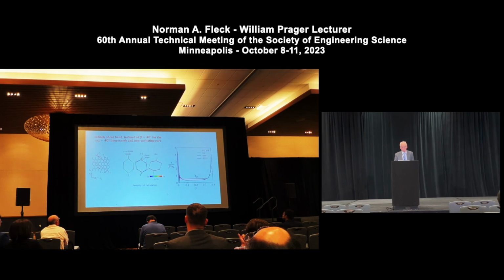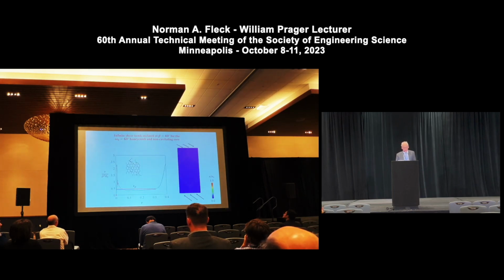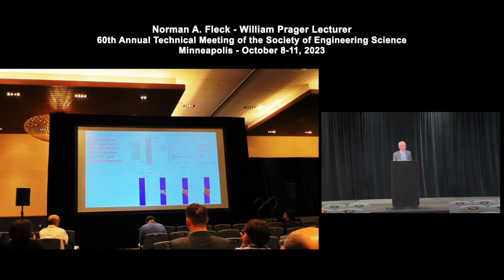So here's the simulation, finite element simulation of such a shear band. When you apply shear stress to it and follow the response of material in that shear band, you indeed get a shear stress against shear strain response, which is softening and then hardening. One can construct the horizontal line and thereby calculate the Maxwell stress that's required in order for this instability to propagate. Here's the finite element simulation just to show what's happening in this shear band, and tau P is the deduced average horizontal stress, as I said. And you can use that calculation of the Maxwell stress to estimate the plateau stress that's observed in the simulation.